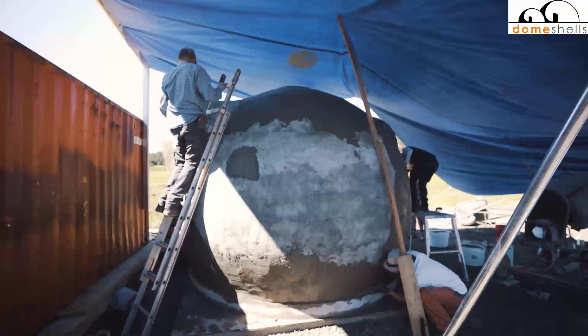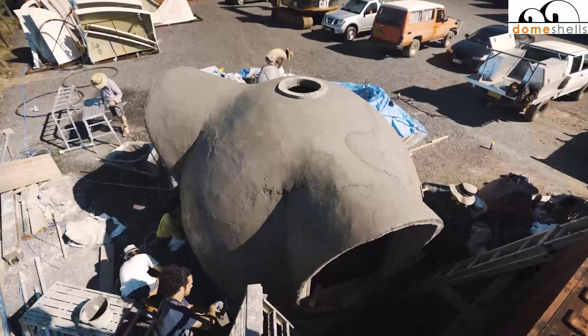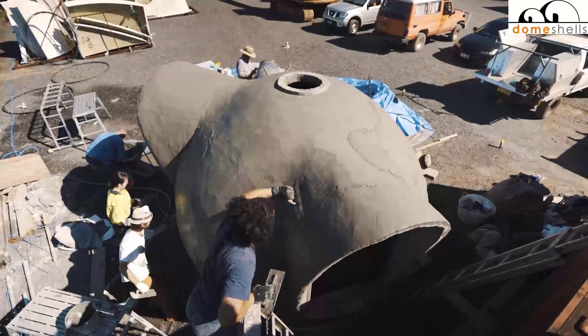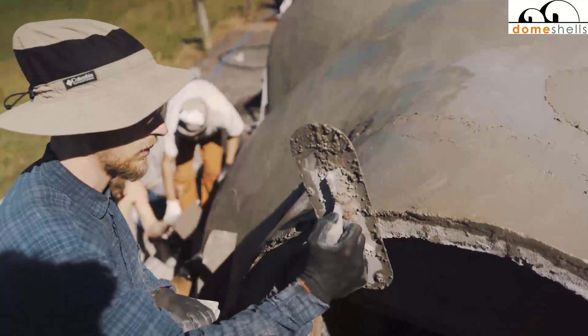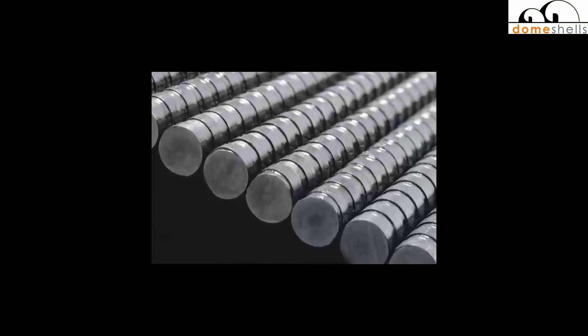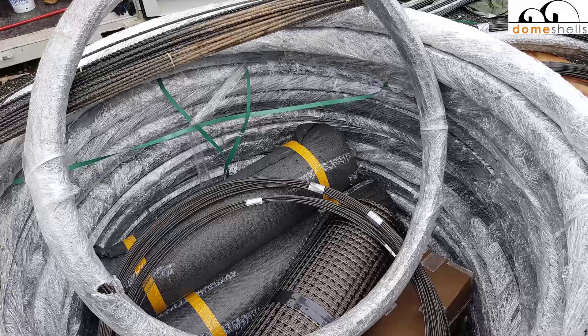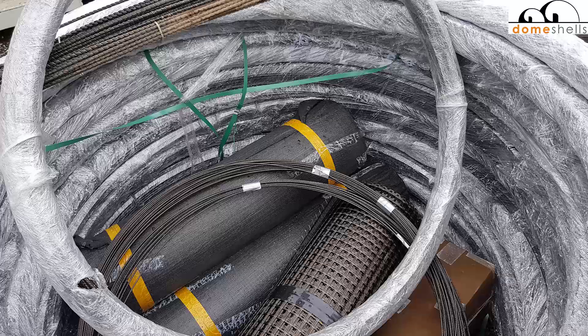It's a system that for nearly 20 years I've been putting all my effort into to simplify, to make the most simple and cost effective method of building a concrete shell structure just like this, so that you, no matter where you are, using very common materials like sand and cement. We use basalt fiber reinforcing, which is a quarter of the weight of steel and twice the tensile strength of steel. It's flexible, perfect for wrapping around compound curves of the domes. It doesn't rust, it has the same thermal coefficient as concrete, and it will last forever.